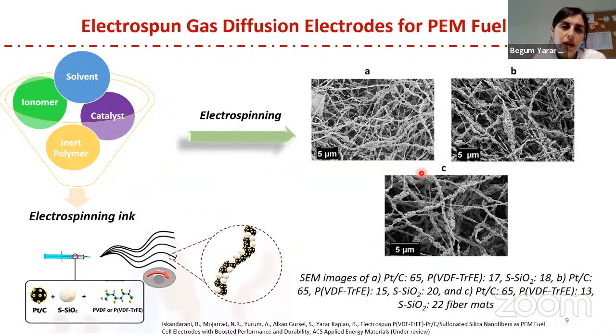I would like to talk shortly about the electrodes for the fuel cells. It's different from the membrane part because we have four components here. We have ionomer, solvent, catalyst, and inert polymer. As catalyst we use platinum on carbon. Here you can see the structure of the electrodes. We obtain electrodes, and we didn't perform any hot pressing because we really need high porosity and high surface area for the electrode fabrication to eliminate the mass transport losses, and to reduce the platinum amount inside the electrode using this high surface area.